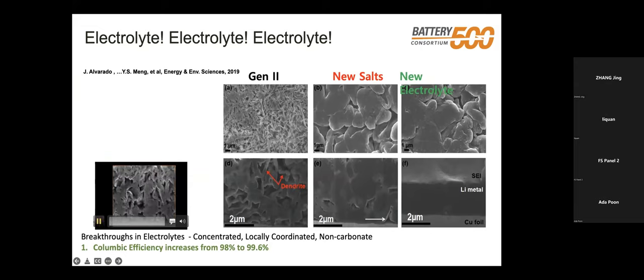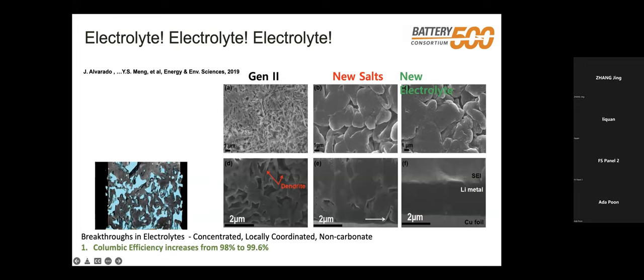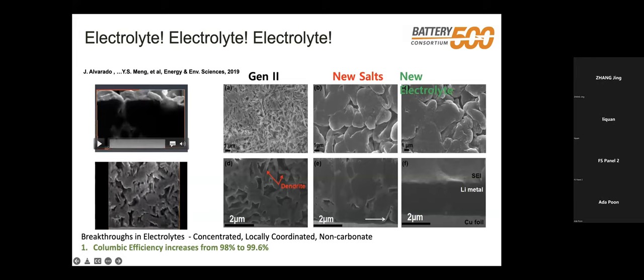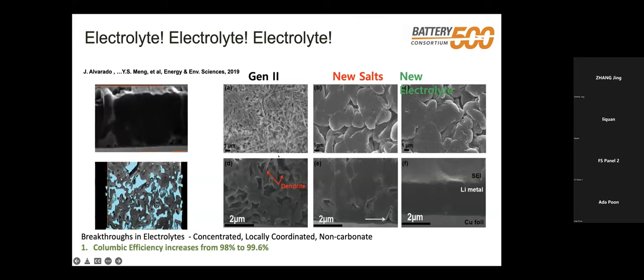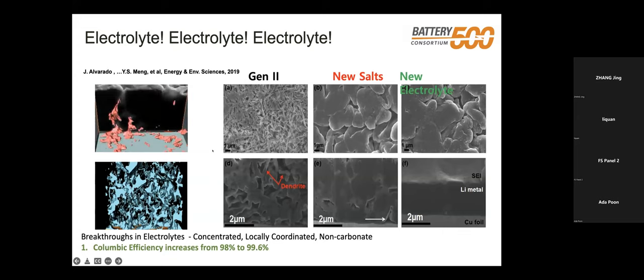So for instance, if I do the 3D tomography cryo-FIB cutting, the carbonate-based electrolyte that was originally catered for graphite is completely not suitable for lithium metal anode, because you will be getting this kind of highly porous lithium metal anode electrochemically deposited. Now, if we change to the ether-based electrolyte, you can see the morphology of these lithium metal are very big, chunky grains, and you have very, very little porosities in this type of electrolyte.